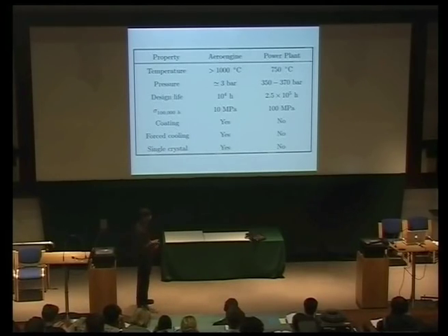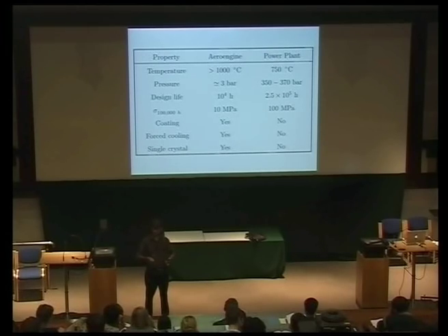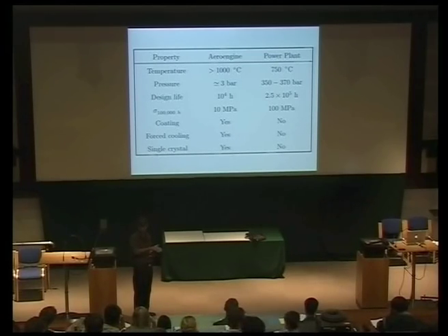This is the stress that the material is required to support after 100,000 hours, okay? 100,000 hours of service. Because the material degrades during service. So you may start off with a much stronger material, but it degrades during service. And you can see that the stress that an aero engine material would have to support is only 10 megapascals, whereas that is 100 megapascals. That seems low, but at high temperatures, these are very high stresses.